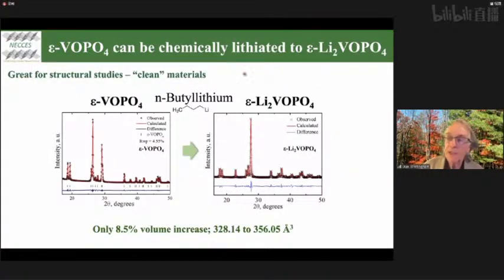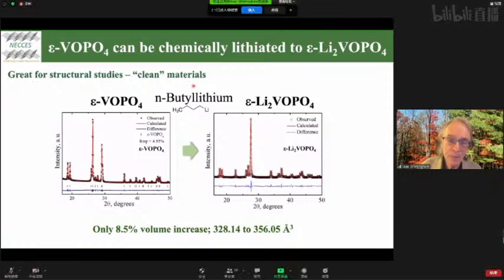So we use a technique originally developed at Exxon, which is a chemical approach, not an electrochemical approach, to make the products. Because in an electrochemical cell, you've got binders, you've got carbon black, and so on, and that complicates the measurements. So at Exxon, we developed the use of butyl lithium. The only byproduct for this is normally octane or butane and other materials. So the clean, easy materials you can get rid of.